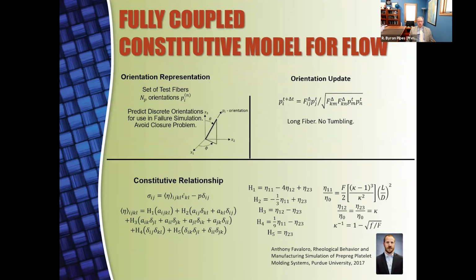So here's the nuts and bolts, if you will. We describe the orientation of the fiber in the same way that it's always been done, but we then map out test fibers. We develop a constitutive relationship which is truly anisotropic, and you can see the tensor for viscosity and shear rate, and of course the pressure term.